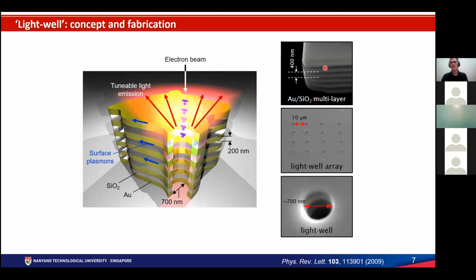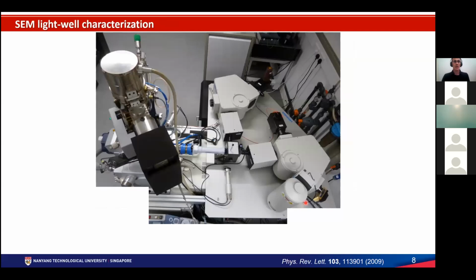It is made by an alternating multilayer of gold and silicon dioxide, about 200 nanometers each, going to a depth of about 2 to 2.5 microns. We have a multilayer, and then we milled it with focused ion beam milling, and in the experiment we changed the hole size. The one I'm going to show you has a diameter of about 700 nanometers. We just shine the electron beam through the hole and detect the light that is emitted. Exactly how we do it: we employ a scanning electron microscope. Ideally, we would like a highly collimated electron beam, but the electron microscope gives you enough depth of focus and collimation, about a few microns, so it's enough to characterize the well.